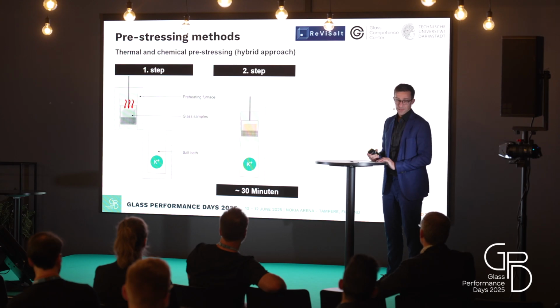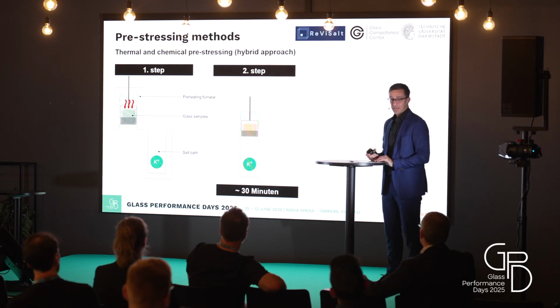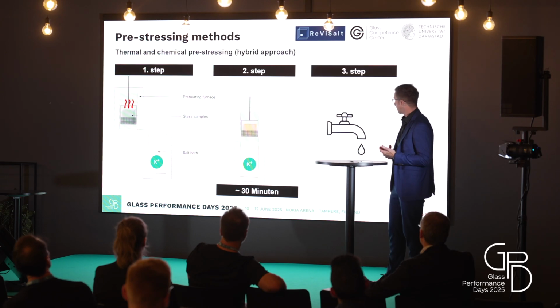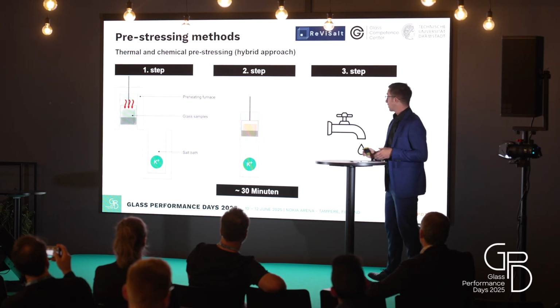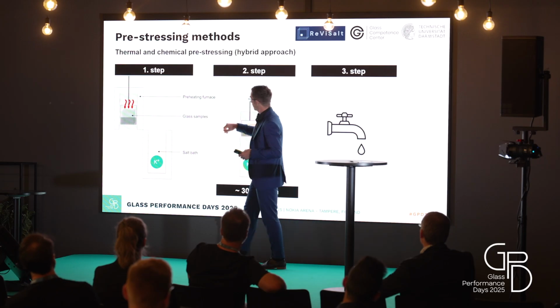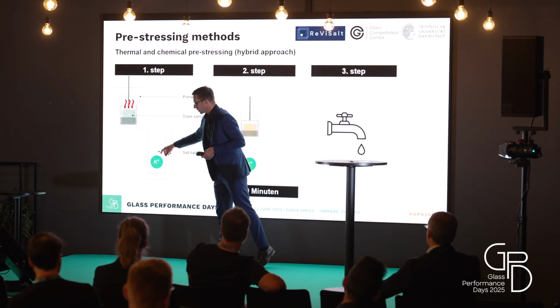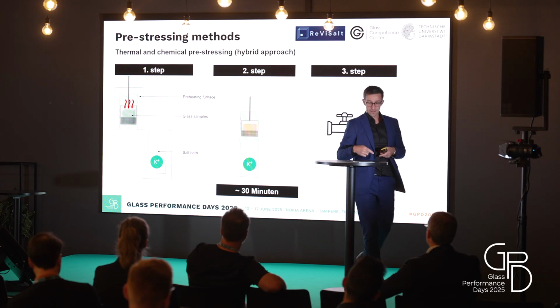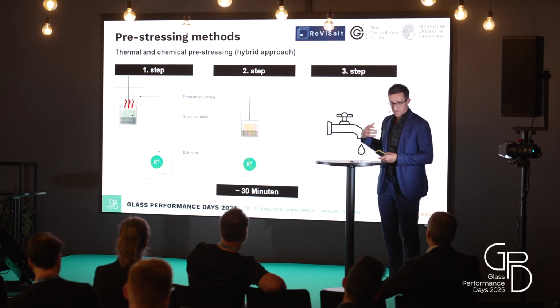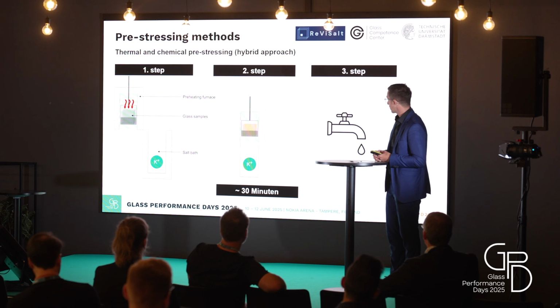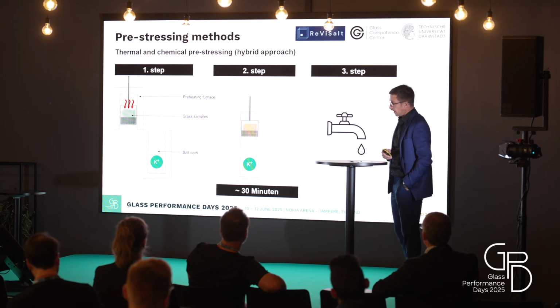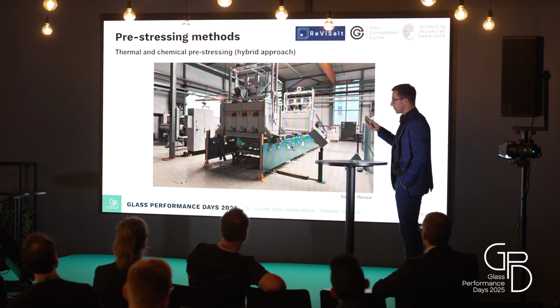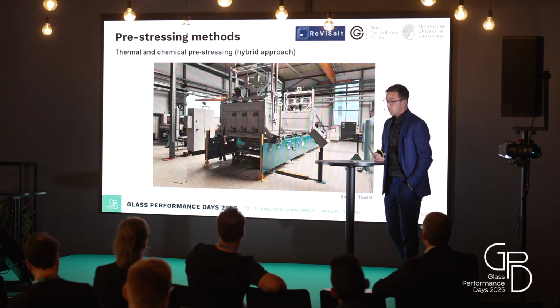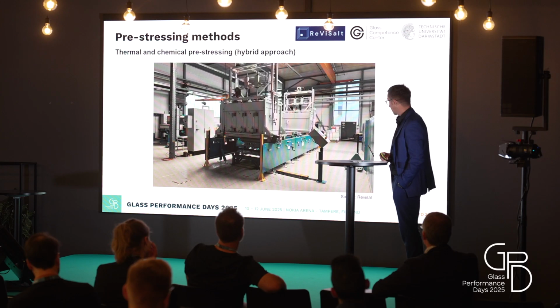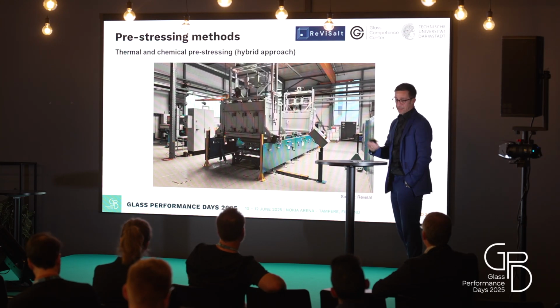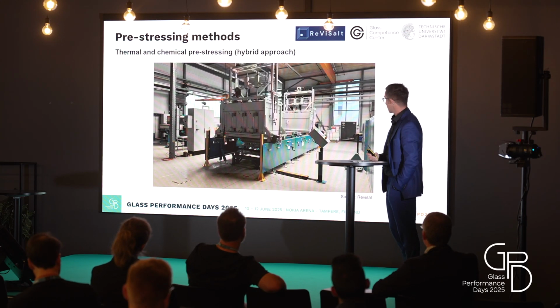It takes more or less 30 minutes and not many hours. And then we have to wash it. And then we have both. Because it's a heat shock, it heats up, we bring it in the bath, rapid cooling. We can transfer a lot of heat, and so we can bring residual stress inside from the thermal part and also the chemical part, and it goes very fast. This was the image before. This was the facility. It was at the moment a batch machinery. We hope that we can do it also not only in batch, but in line.